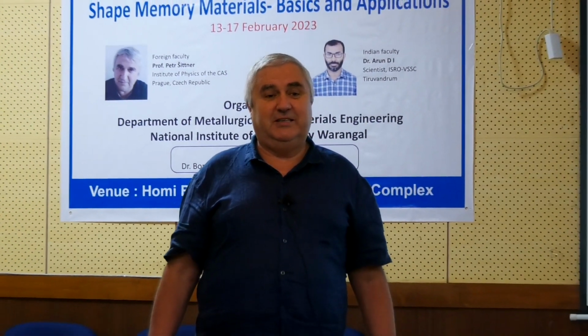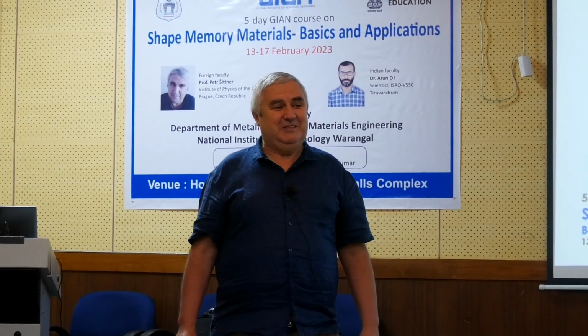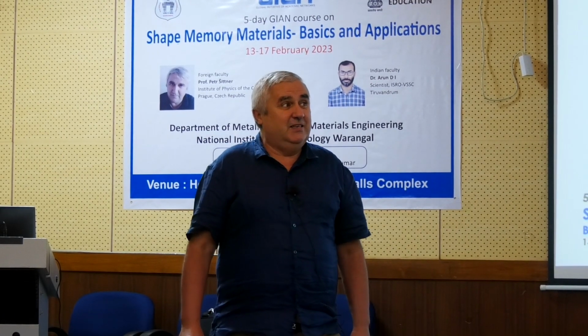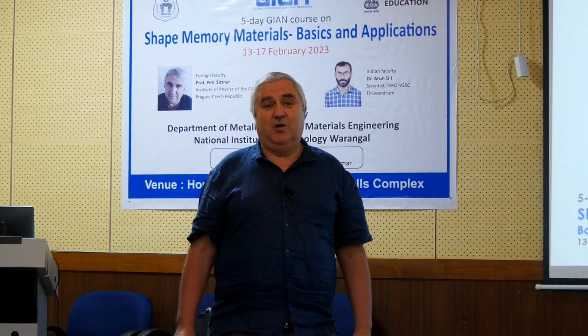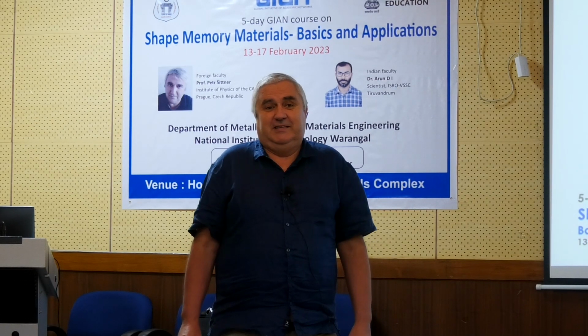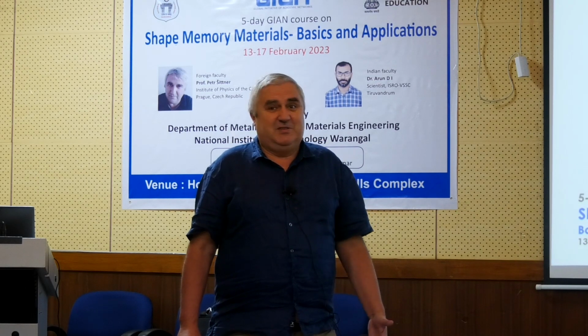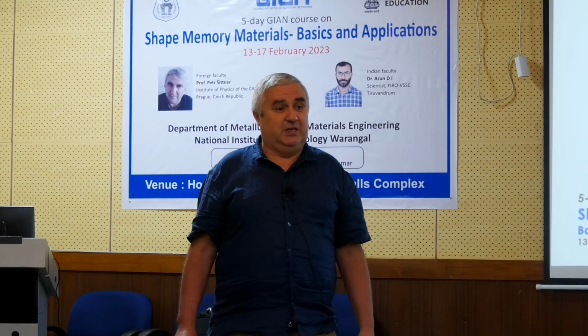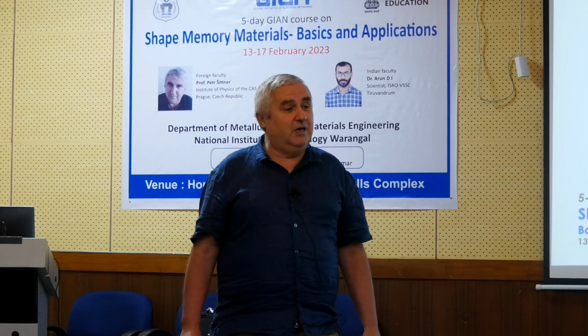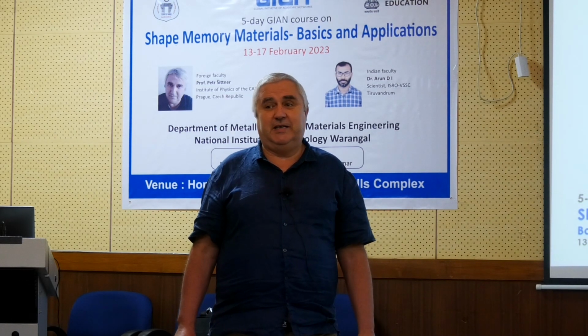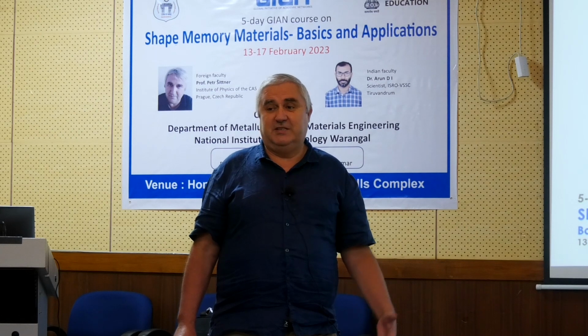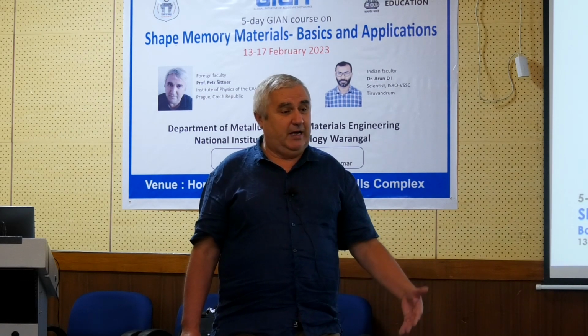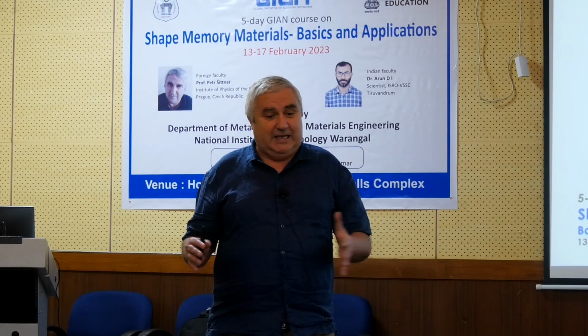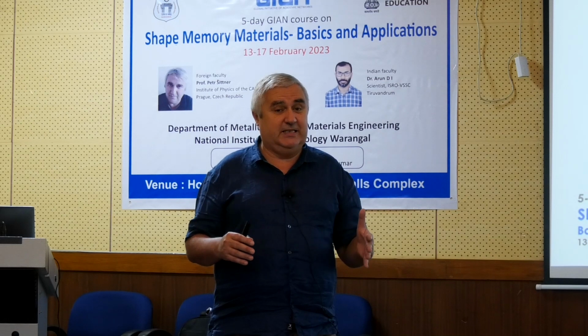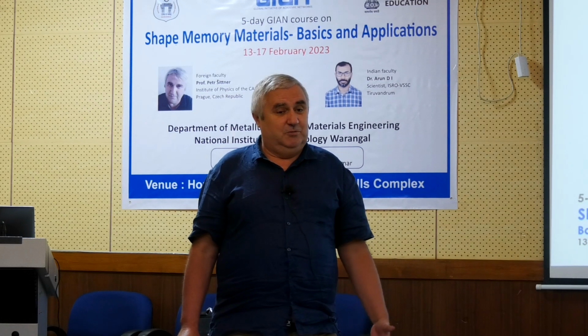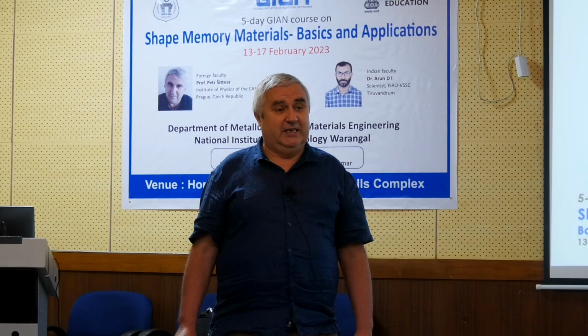Today we will start our NiTinol session, and it will go almost to the end. But it doesn't mean that NiTinol is the only shape memory alloy we should look at. It only means that it exists in some semi-product components, so engineers can easily use it. And if I'm speaking about NiTinol, I'm speaking about not only binary nickel titanium, but any kind of alloy derived from NiTinol, which could be titanium, copper, titanium, iron. Those alloys have slightly shifted transformation temperature, slightly different hysteresis, but basically you can apply the knowledge from NiTinol also to those materials.